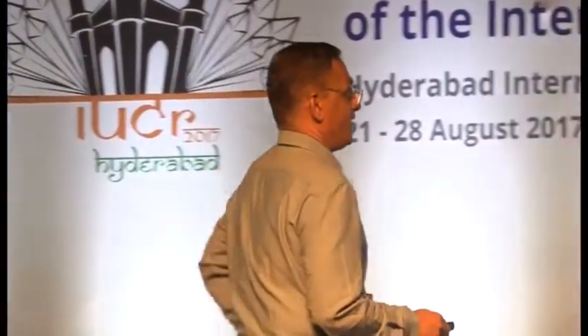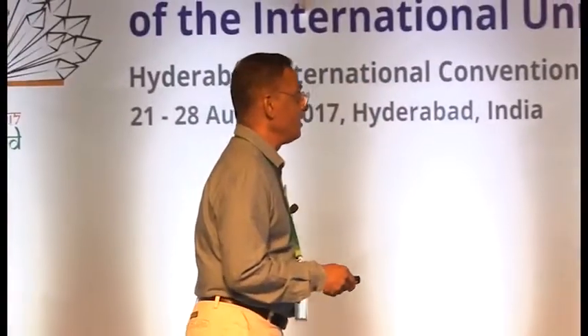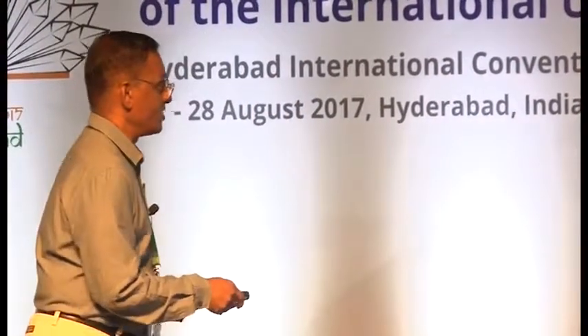When you look at the packing structure, there's a channel going through. Actually, you have diethyl ether that could easily be removed. So you're wondering, even with such a weak interaction, although in organic crystal engineering the hydrogen bond is considered very strong, even the hydrogen bond between the water and the diethyl ether is able to retain diethyl ether well above its boiling point. Of course, we have done some TG-IR and TG-MS to show that this is what is happening. You can see a direct correlation between the temperature and the diethyl ether release. We should be able to control the retention of diethyl ether in these simple metal complexes.